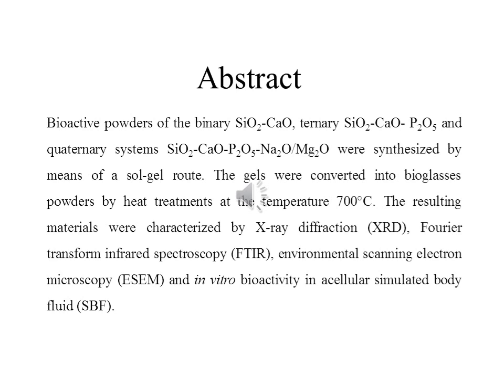Bioactive powders of the binary SiO2-CaO, ternary SiO2-CaO-P2O5 and quaternary systems with sodium and magnesium were synthesized by means of a sol-gel route. The gels were converted into bioglass powders by heat treatment at a temperature of 700 degrees Celsius. The resulting materials were characterized by X-ray diffraction, Fourier transform infrared spectroscopy, environmental scanning electron microscopy, and in vitro bioactivity in a simulated body fluid.